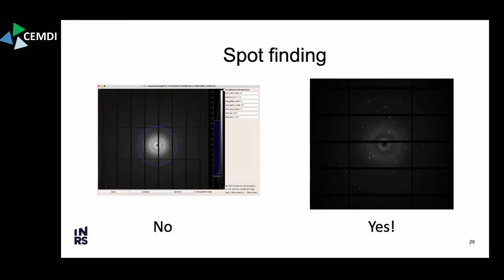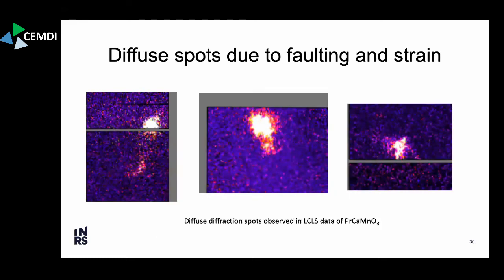And the way that this works is you can't just simply threshold, because you actually have a lot of variation in the background. And so what most people do is a windowed filter, where you look at say a 10 by 10 window of pixels, and you go through the entire image, and you look and see if you have any outliers from the median value or the background value. And you define that as a potential pixel or set of pixels that has a spot.